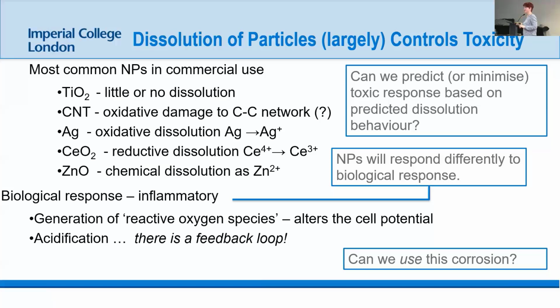But each of these particles is going to respond differently to that biological response, right? The silver will go, well, I'm being oxidized and I'm acid, so I might go a bit faster. But the ceria is actually stabilized by that high potential. So there isn't a one-size-fits-all. What we're trying to do in my group is predict, at least minimize the toxic response, recognizing that different particles respond differently, and there will be a feedback loop, right? So if you've got an inflammatory response that causes further dissolution, say acidification dissolving the zinc, then you set this biological cascade that increases the inflammatory response that will then make the particle dissolve faster. So we have to remember there's a feedback loop.